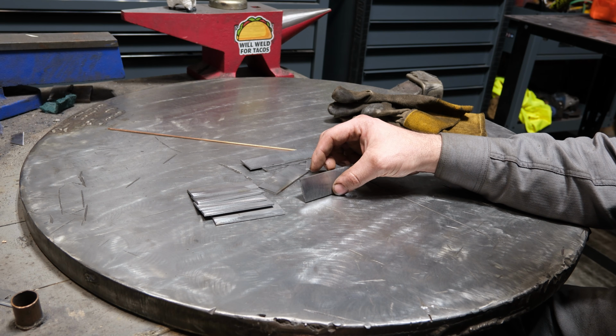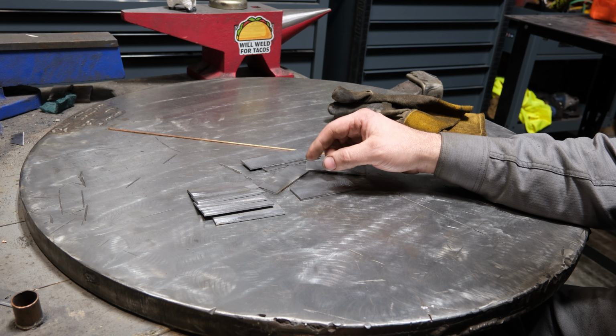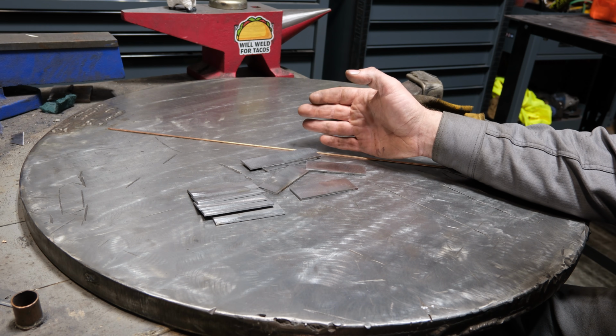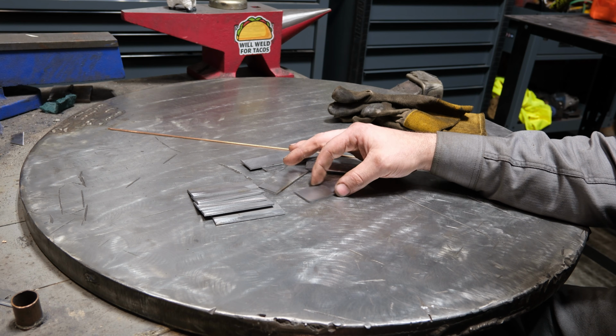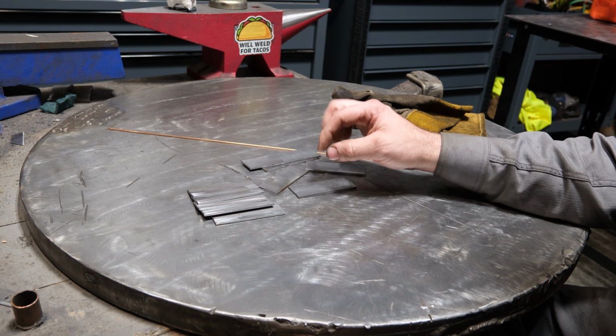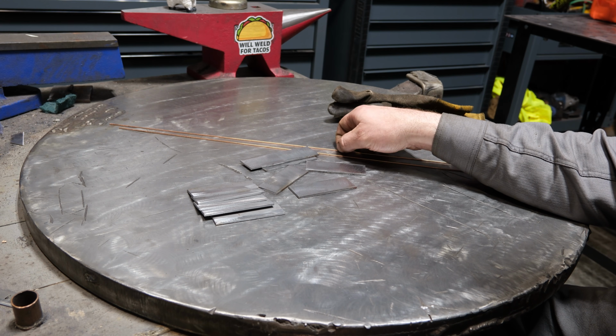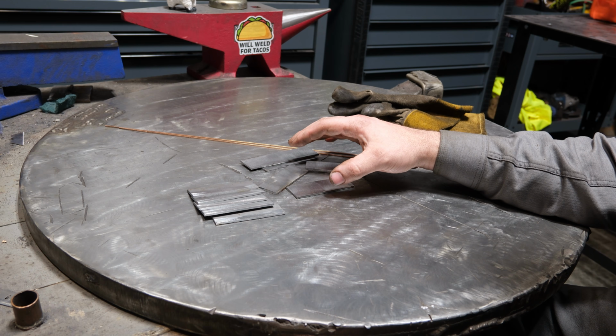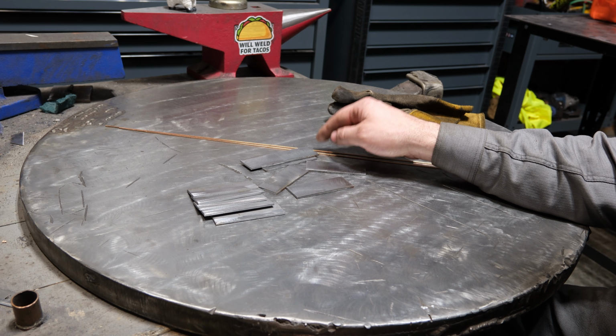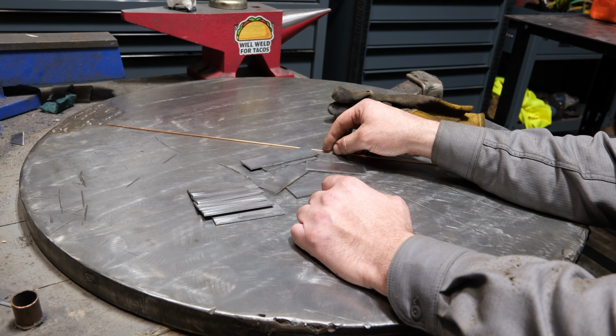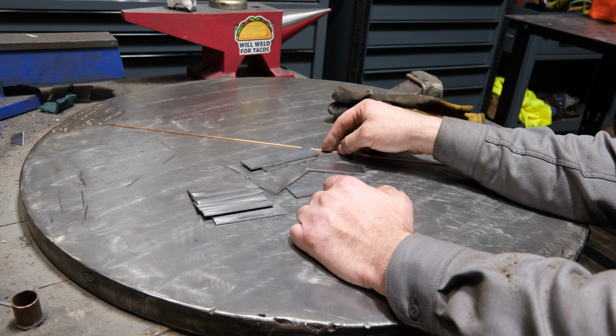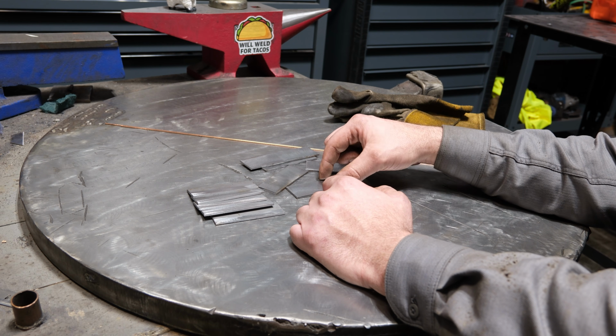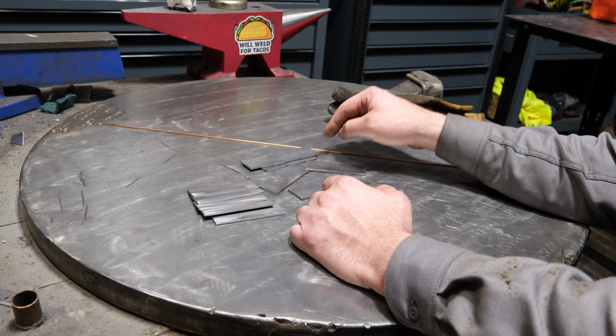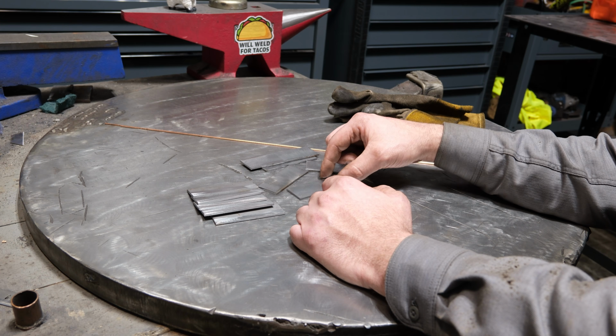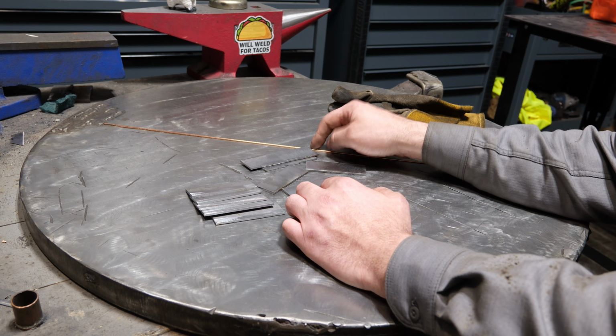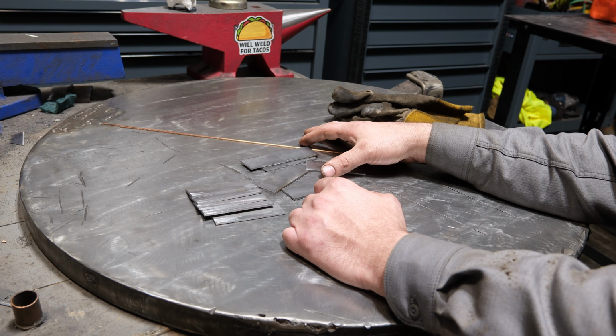Amperage wise, I'll set the machine for 140 amps, maybe more, and then we're going to use the pedal to control it. If you're doing lift start or scratch start, I would suggest somewhere around 100 to 120 amps for this. Now for filler size, I have 1/16 or 1.6 mm filler. You can use thinner filler. I would not recommend bigger than this. And I don't know why, but a lot of places, like Harbor Freight, for example, only sell 3/32 rod. And for steel, that's really too big to be welding a lot of stuff like this, simply because you're going to need too much heat to melt that rod and you're going to end up making cold welds. So 0.45 or 1/16 filler is what I would recommend.